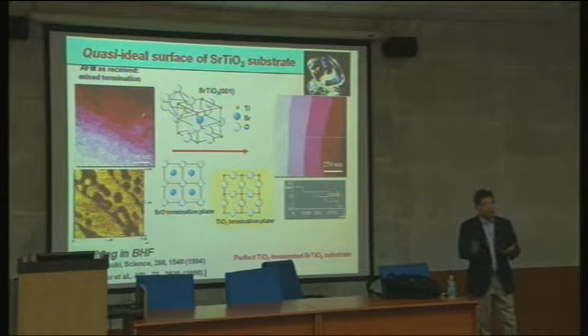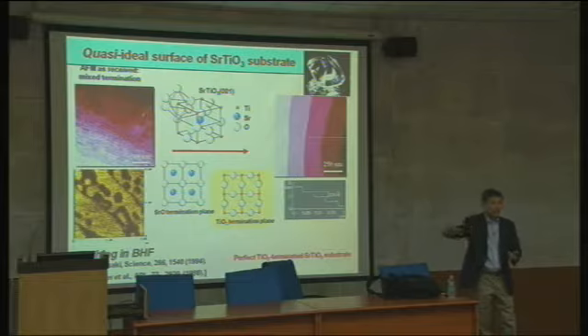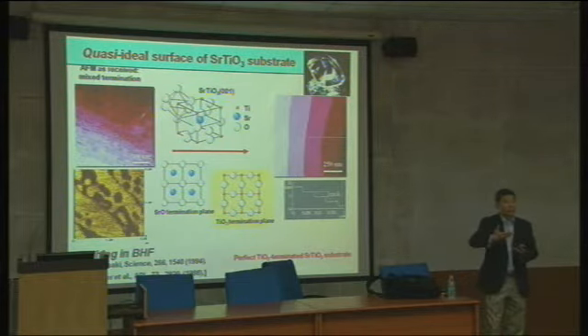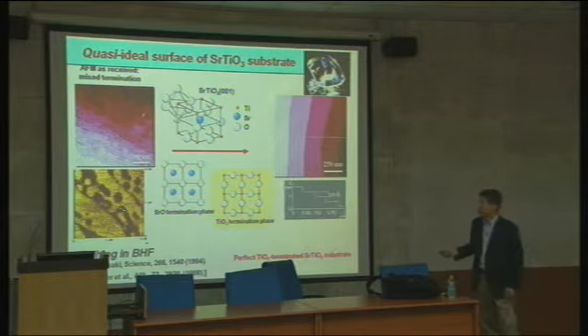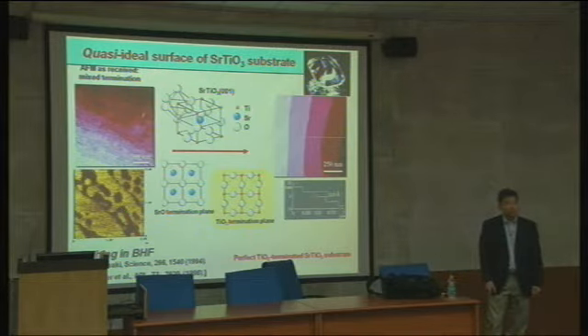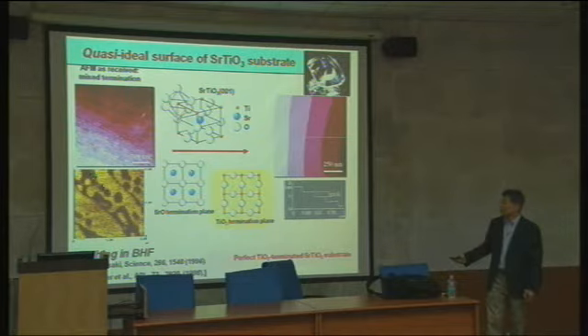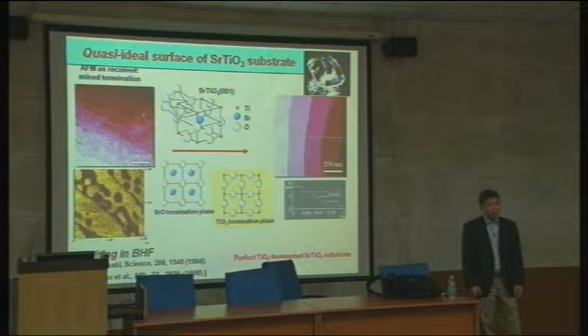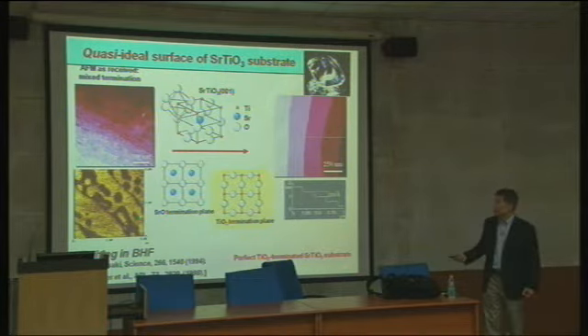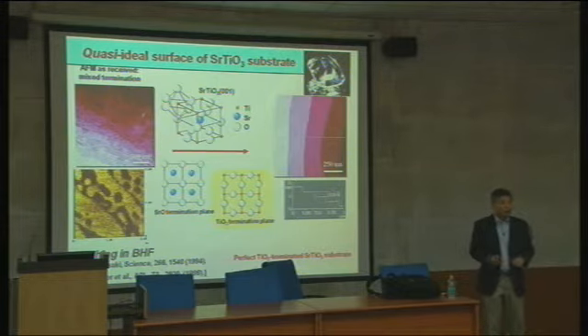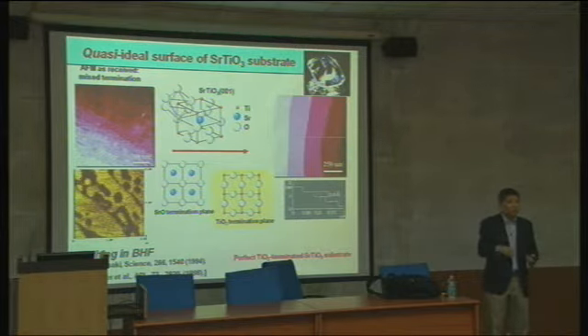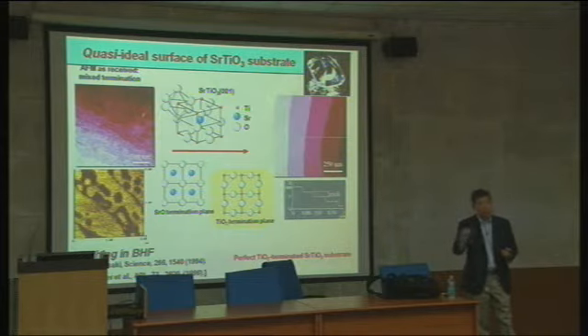This is done by what we call friction contrast. When you do an AFM scan, your lateral scan can actually see that there's friction between the AFM tip and the surface atoms, and depending on your termination layer you have a different friction, and you can see very strong contrast between different terminations. Then we grow the thin film on top, and in this region and that region, the film grows differently. For example, we grow one material and it lays down very flat, beautifully. And this region doesn't wet, like a water droplet that doesn't wet, and islands grow. So a very strong contrast, two very different regions.